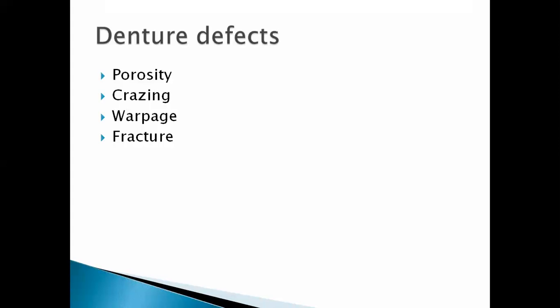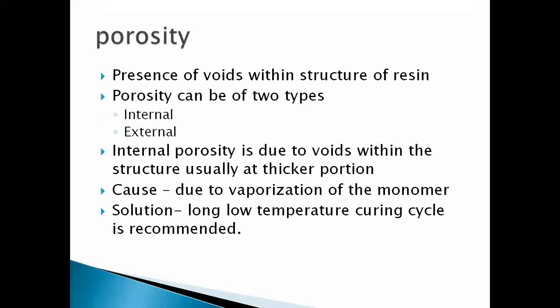Okay. So what kind of defects can occur in denture processing? These are porosities, crazing, warpage, or fracture. Porosities can be internal or external. Internal porosities are the porosities that are well below the surface, not near the surface. This generally occurs in the thicker portion if the curing cycle is not adequately followed or there was too much boiling of water. If you don't follow the curing cycle correctly, internal porosities can occur.